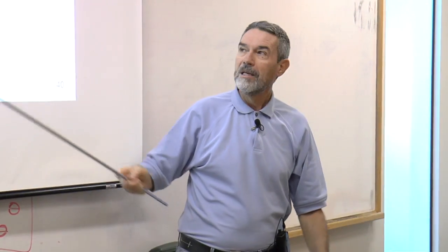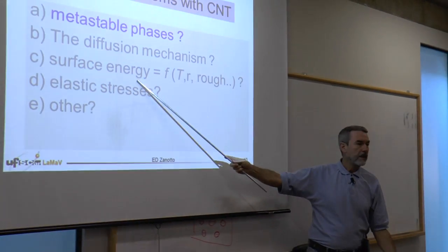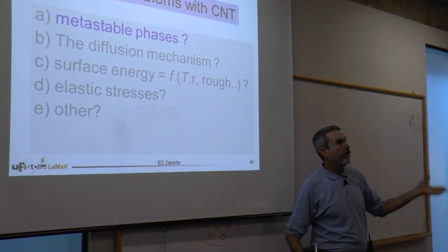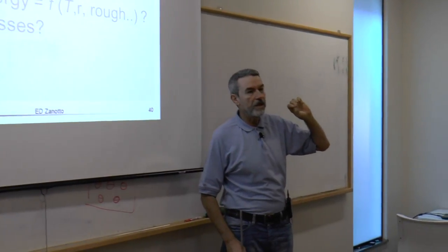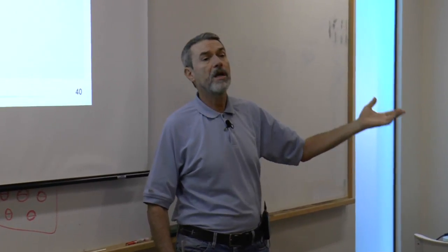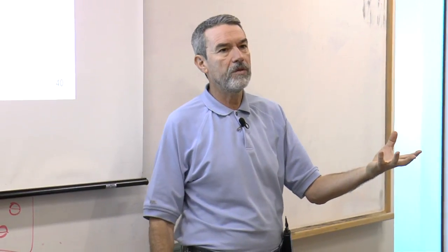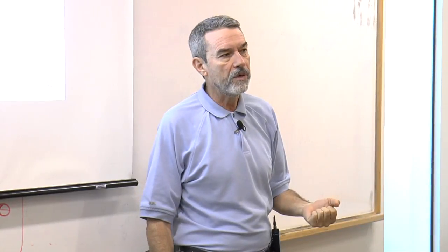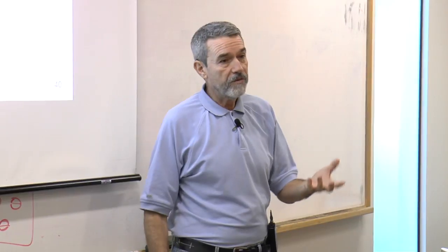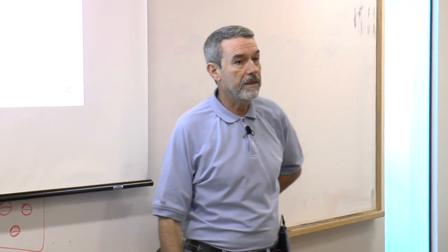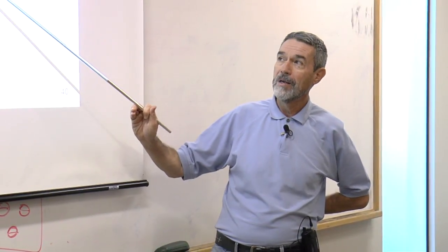Or maybe the surface energy. So far, the classical theory assumes that the surface energy is constant. It does not depend on the size of the nuclei or on the temperature. But maybe it does. The surface energy is a thermodynamic quantity, so maybe it does.